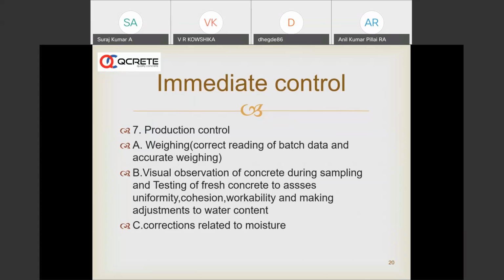Proper control of slump is indirectly proper control of water cement ratio, and this can be achieved by properly feeding the moisture on 20 mm, 12 mm and sand to the software, the batching computer. Moisture is fed at least 2 to 3 times on a monsoon or rainy day.